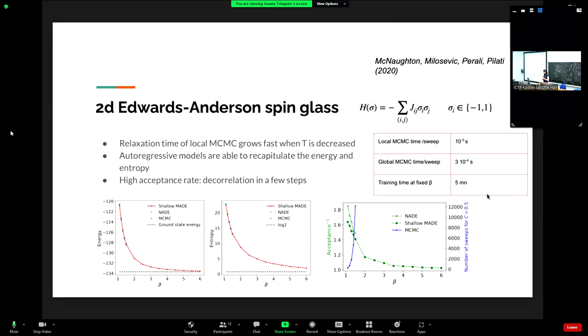What is interesting in this model is that the relaxation time of local MCMC grows very fast when T is decreased, and you can see it on the last plot, the blue curve. It's the number of sweeps you need to decorrelate as a function of beta, and you see that for beta equal 1.5, you already need more than 10,000 sweeps to decorrelate, and actually it's not possible to go to higher beta. It becomes too slow. So local MCMC doesn't work at low temperature in this model.